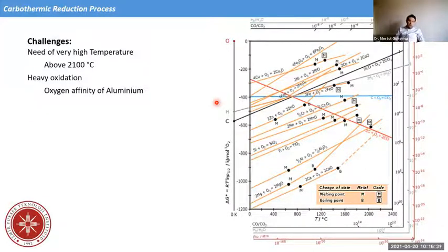And it is not only cost, because if you look at the aluminium diagram, the aluminium oxide line is very low. It has very low minus delta G. This means aluminium oxide is very stable. So aluminium oxidizes when it finds any chance. If you try to process a metal above 2100 degrees Celsius, the oxygen affinity of aluminium also becomes a very big problem. So if you want to do it, it has to be under a protective atmosphere. And a protective atmosphere for aluminium is not very easy. It is not just blowing argon, because aluminium can oxidize even with ppm range of oxygen in the atmosphere. But this is a big challenge.